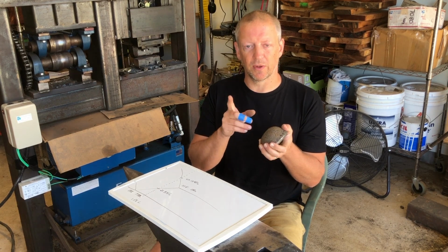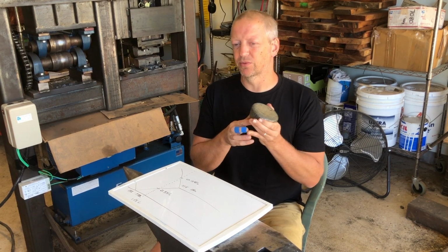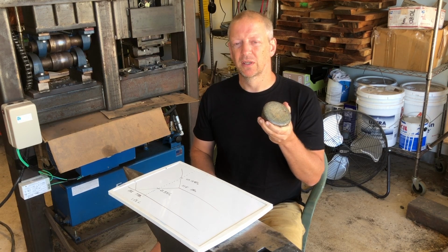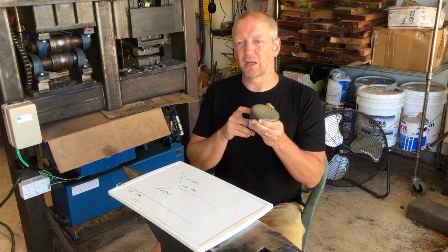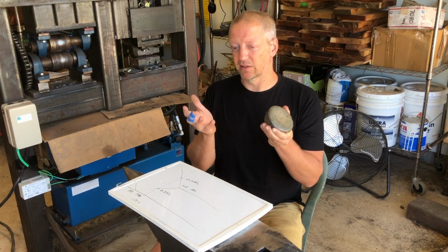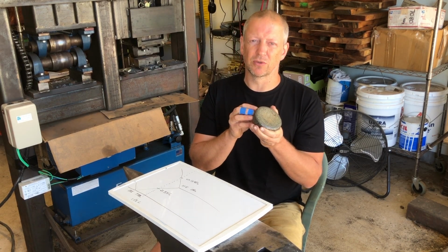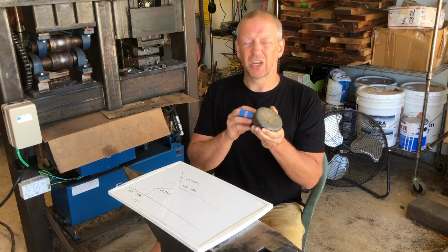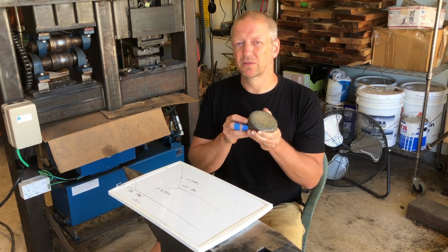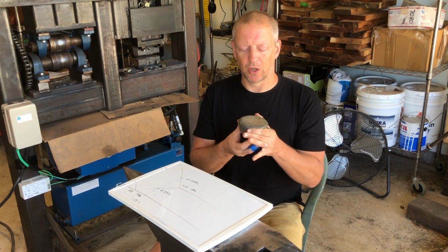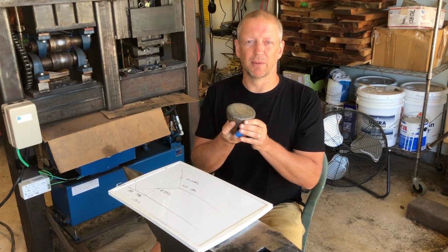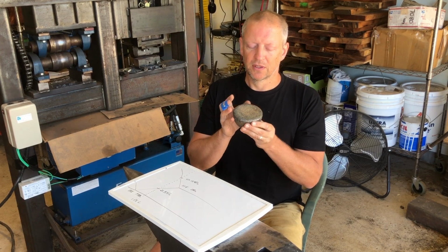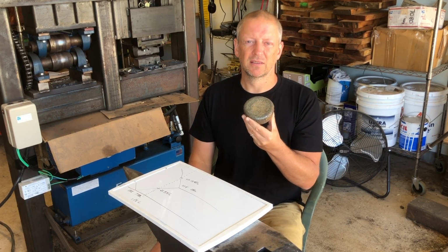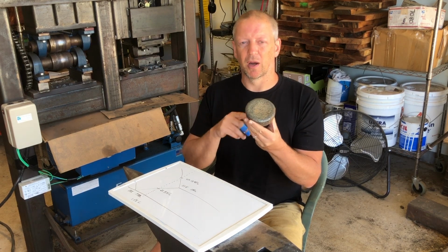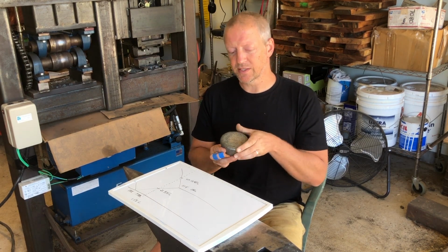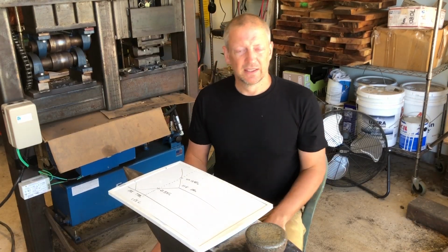I will note, actually, one thing about roasting. If you decide you're going to roast back in the crucible, keep in mind that depending on what type of crucible you're using, like let's say a clay graphite crucible, you're going to actually pick up carbon from the crucible during that roast. So in that situation, you might want to do what Pendray and Verhoeven would do, of packing it in iron oxide to avoid picking up carbon from your crucible. So that's the roast for now.